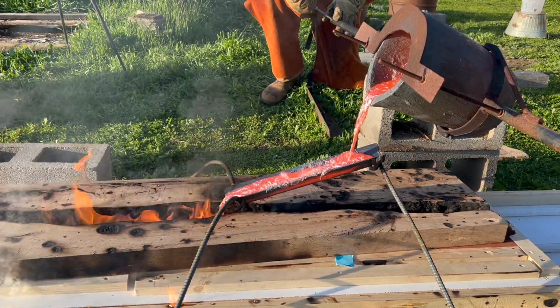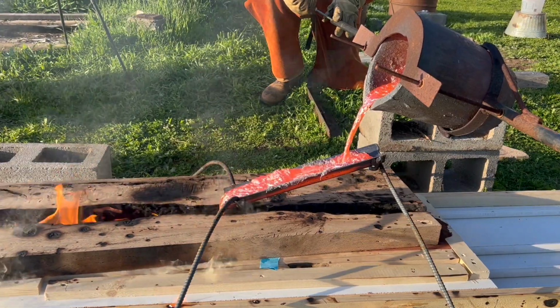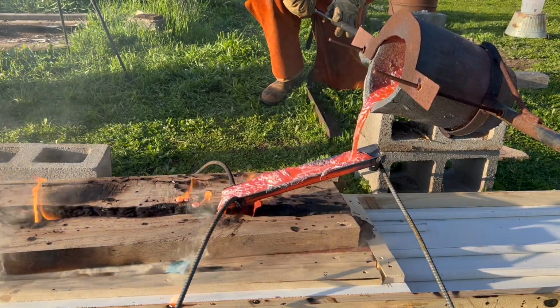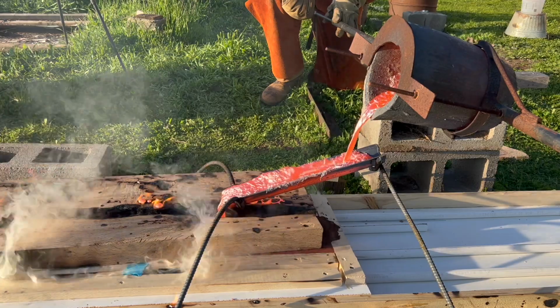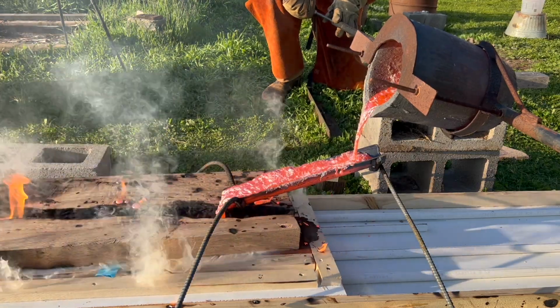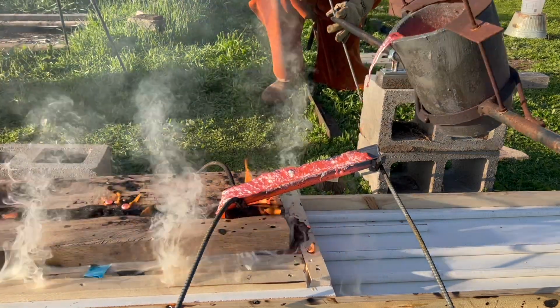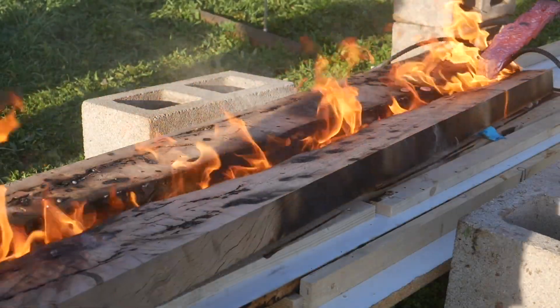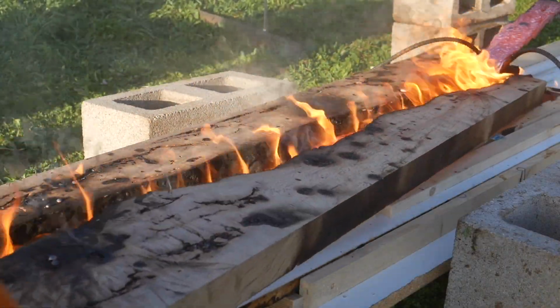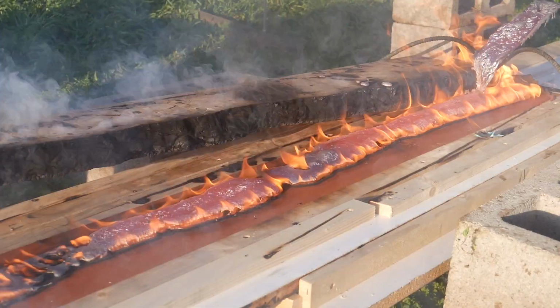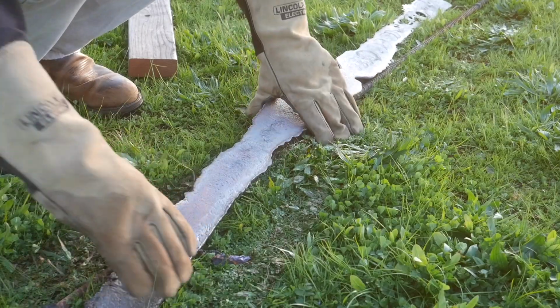It also doesn't help here that the bronze was sticking to the luge even worse now, which I guess heating up the luge made it worse in the end. The luge was supposed to help reduce turbulence in the casting, but obviously it's not quite helping here. This casting didn't fill in all the way, in large part because like 50% of the bronze got stuck to